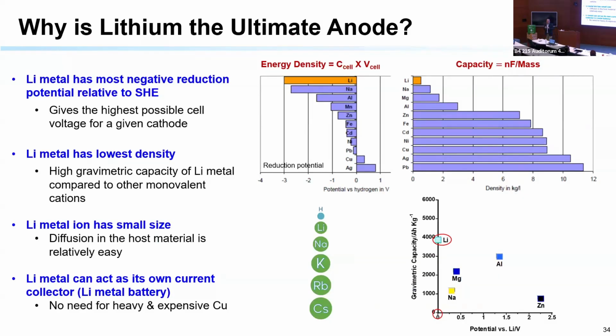The lithium is always moving. It's called the rocking chair battery, because the lithium is moved from anode to cathode into the electrolyte. Being small makes this mobility fast. Lithium metal can act as its own current collector. If you want higher energy density, and instead of using a graphite anode, you use a lithium anode, you can get significantly higher energy density. And as I mentioned, this is one of the active areas of research. If you want to really realize battery-based flights, you are going to need to use lithium metal.